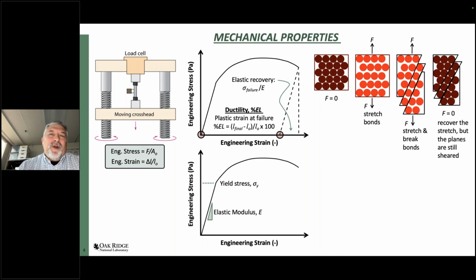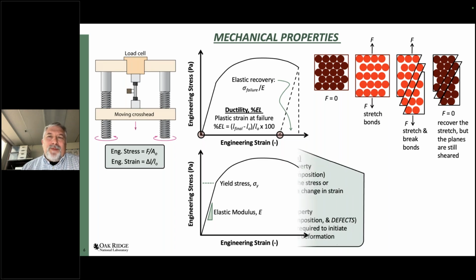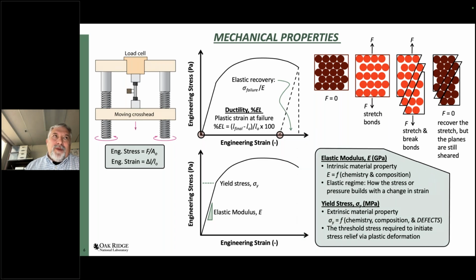These are two of the most important properties that we need in order to be able to have some idea of how to understand what's going on with the pressure within those morphological defects, all right? So the elastic modulus is an intrinsic material property, and that's because for a fully dense material, it's basically just a function of the chemistry and the composition, right? It doesn't depend on the processing conditions, right? And so the modulus is just defined as this slope here of the linear elastic portion of the stress strain curve, right?